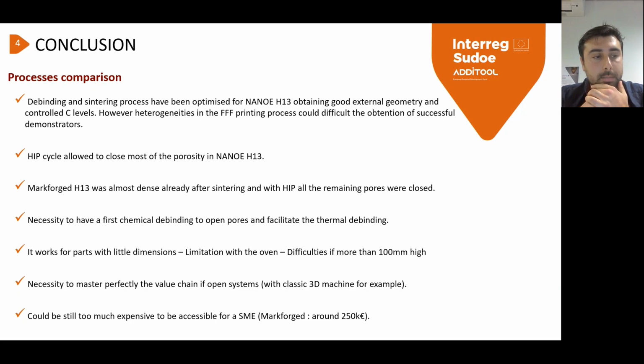But we have analyzed that it is necessary to have a first chemical debinding to open pores and facilitate the thermal debinding, and to have also a cylindrical oven, not cubic. Okay, so chemical debinding is very necessary to open channels and to reduce a lot the time of debinding and sintering. This kind of technology works for parts with small dimensions, less than 100 millimeters. But we have a lot of limitations with the oven and difficulty if it is more than 100 millimeters high.